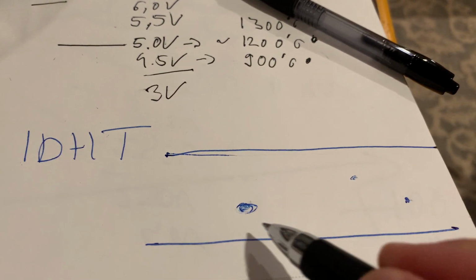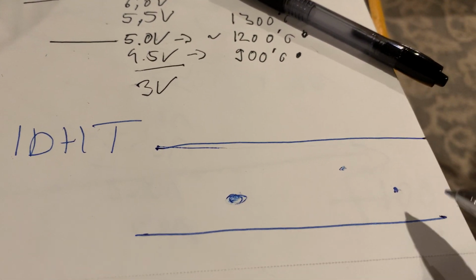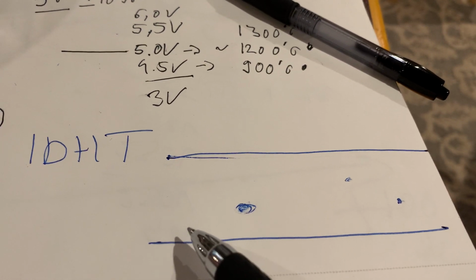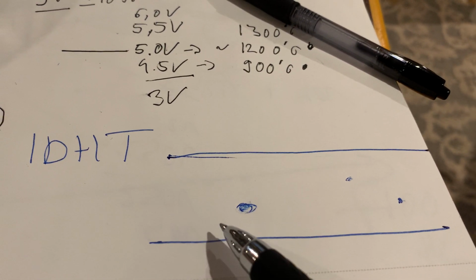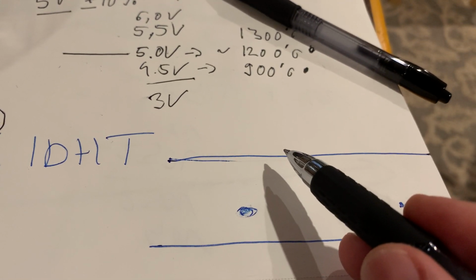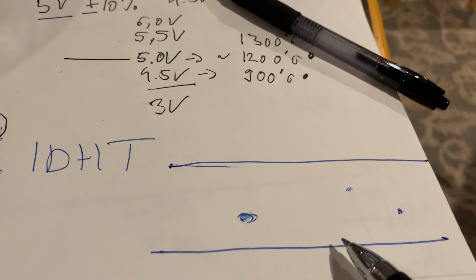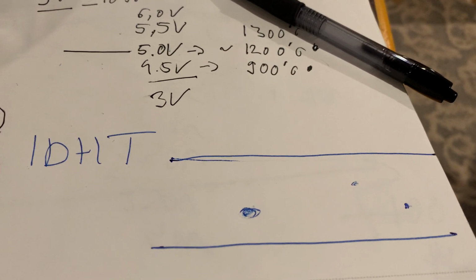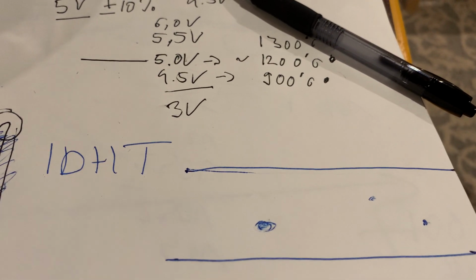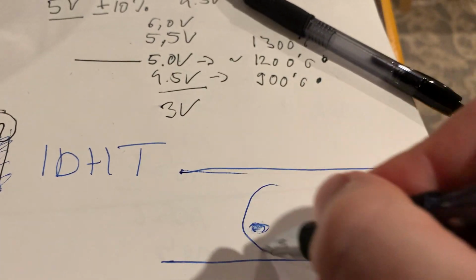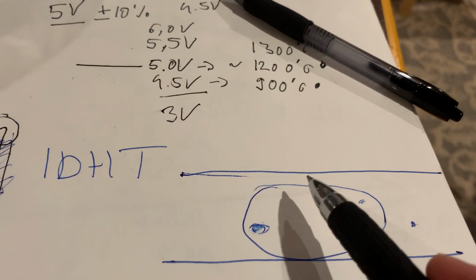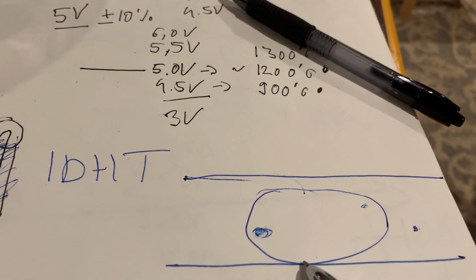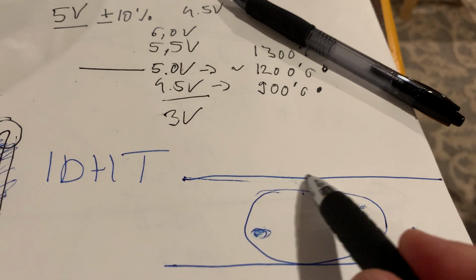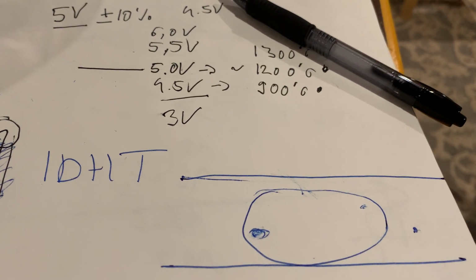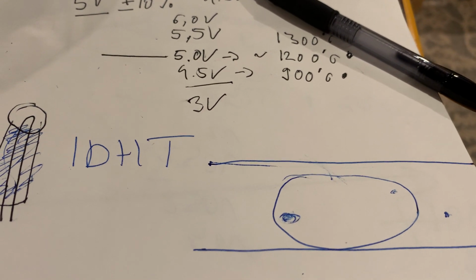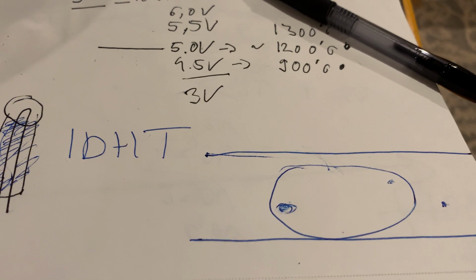So over time, as you switch it on and off, with each heating and each cooling cycle, you are heating it up from basically 20 degrees Celsius to 1200 degrees Celsius, and then cooling it down from 1200 to 20, and each time you turn your amp on and off, hundreds of times during the lifetime of the tube, these impurities are getting worse and worse and worse. And after a while, when your impurity is so big, then your filament will stop conducting. It might physically snap, or it just might change the resistance of the filament to such a degree that it cannot do its job anymore. And then your tube will die because your filament cannot work anymore.